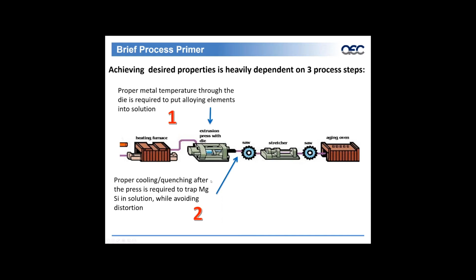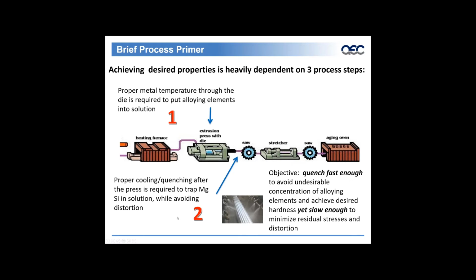Second part is proper cooling and quenching after the press. This is required to trap the mag silicon in solution while avoiding distortion. So the objective of this, and this is a key factor in the extrusion process and what drives a lot of cost, what drives a lot of tolerances associated with product, and has a big impact in the specific alloys that are achieved relative to the performance need. But the objective here is to quench fast enough to avoid undesirable concentration of alloying elements and achieve desired hardness, yet slow enough to minimize residual stresses and distortion.